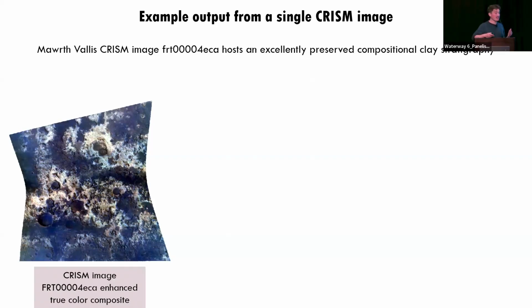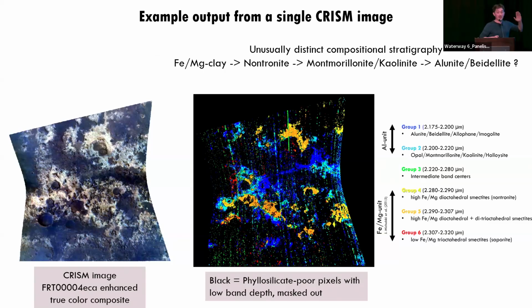So we have so much data. I'm just going to show you the spectral database output from one single CRISM image. And this is a place in Mawrth Vallis, and it's a really excellently preserved example of a compositional clay stratigraphy. So the colored map I'm showing you now is the same colors as those different band center groups that I was showing you on the earlier slide. So we can see really interesting spatially coherent patterns in where these clays are located.